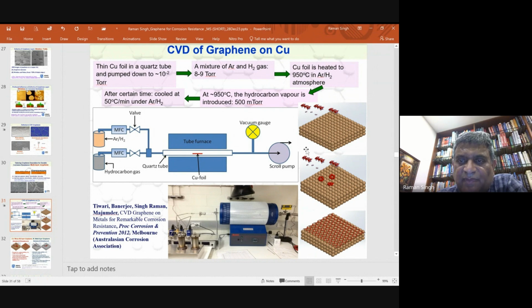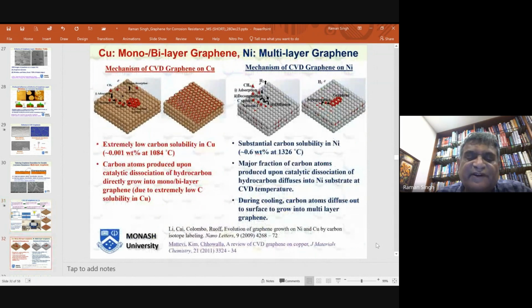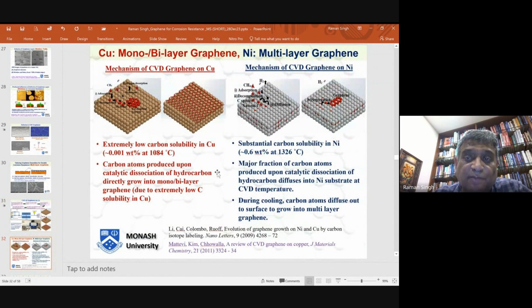Also I would like to mention one particular thing, that there is a stark difference in the mechanism by which graphene develops on copper and graphene develops on nickel. As I said, both copper and nickel are very good catalysts for splitting hydrocarbon that is required for graphene development. Copper does not have much solubility of carbon. So whatever carbon you generate, it immediately arranges itself to develop graphene if you maintain right partial pressure. So copper can only develop single or two-layer graphene because the carbon that you produce cannot dissolve in copper, which has very poor solubility, very low solubility, insignificant.